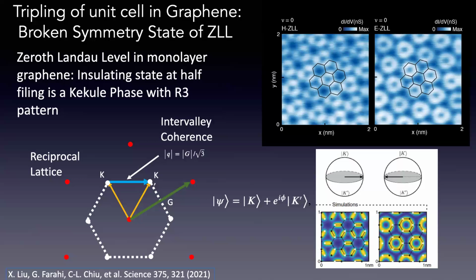And you can think of this on a Bloch sphere, just like I showed you on the previous slides for magic angle graphene. Here you just have one Bloch sphere, and the ordered state is one in which you make a coherent superposition, and this is represented by this vector. Now, interestingly enough, and this is going to come later in the talk, depending on what is the orientation of this angle, the density of states in real space can actually make a difference. So this we discovered in modeling graphene. And just to be sure, K and K prime are valley indices.